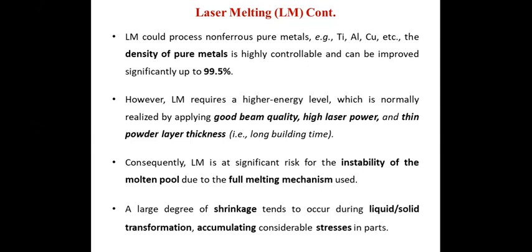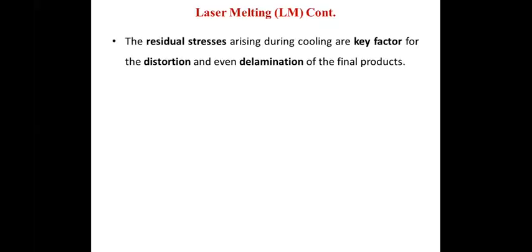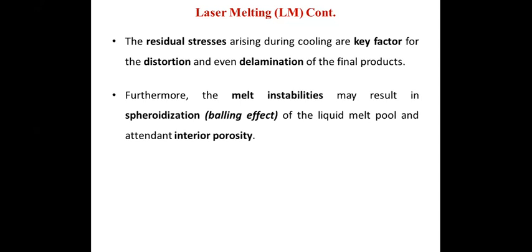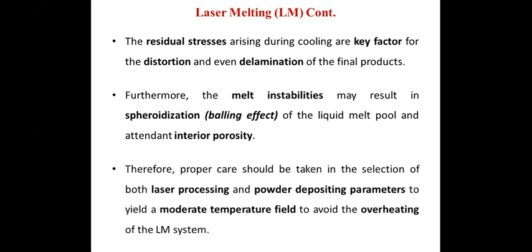A large degree of shrinkage tends to occur during liquid-solid transformation, accumulating considerable stresses in the parts. The residual stresses arising during cooling are a key factor for distortion and even delamination of the final products. Furthermore, the melt instabilities may result in a balling effect of the liquid melt pool and attendant interior porosity. Therefore, proper care should be taken in the selection of both the laser processing and the powder deposition parameters to keep a moderate temperature field and avoid overheating of the laser melting system.